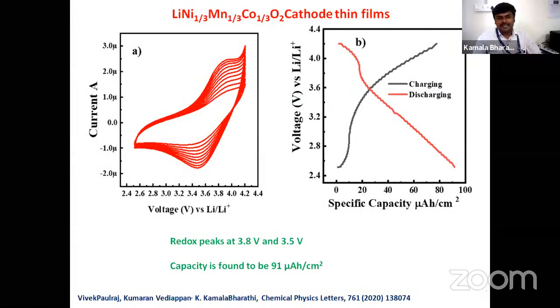And this is the IV or CV curve for this thin film. So this thin film shows a very good electrochemical activity, and its redox peaks are observed at 3.8 and 3.5 volt, which is the fingerprint of this material. Also, we were able to get the capacity in the order of 91 microampere hour per centimeter square at first cycle. So this tells that the films we have fabricated have electrochemical activity.